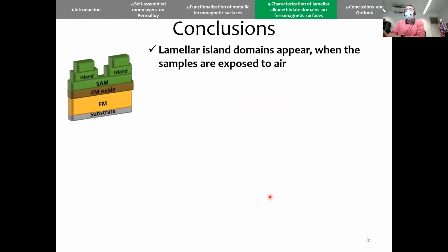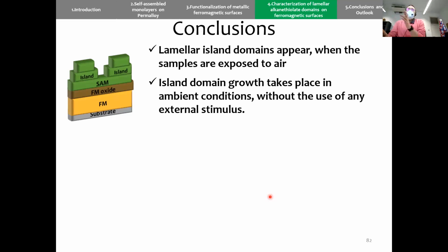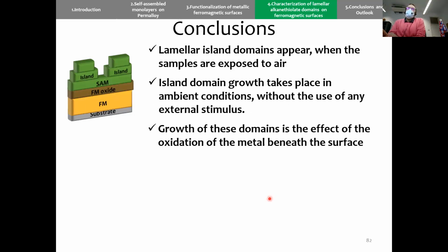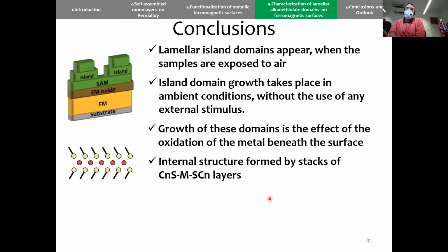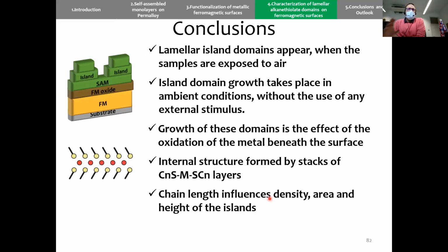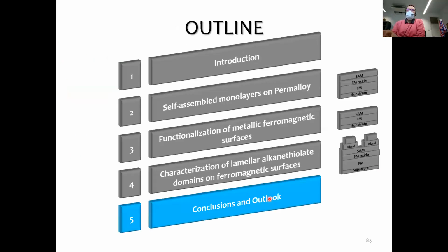So just to conclude, these domains appear when exposed to air. It doesn't need any external stimuli, and it is the effect of the oxidation of the metal beneath the surface. And we imagine this is the internal structure, and we have proved that the chain length of the molecule we use to functionalize the surface can give us different lamellar structures.